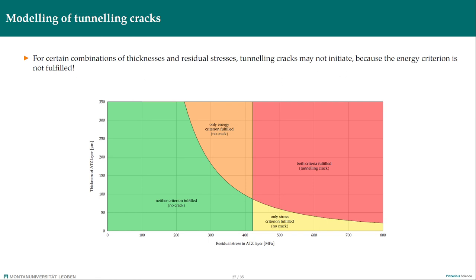The light yellow area in the graph shows a region where tensile residual stresses in the layer overcome the strength of zirconia toughened alumina, that is material which we used, but cracks should not initiate nevertheless because the energy criterion is not fulfilled. And you might doubt what is the strength, but that is a topic which I would like to keep for discussion or later for communication.